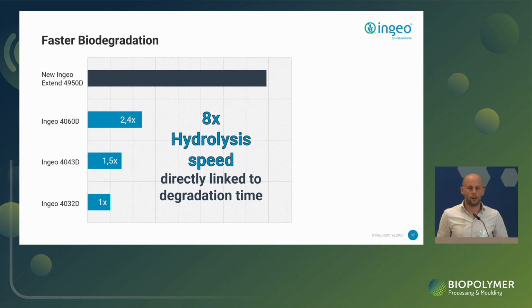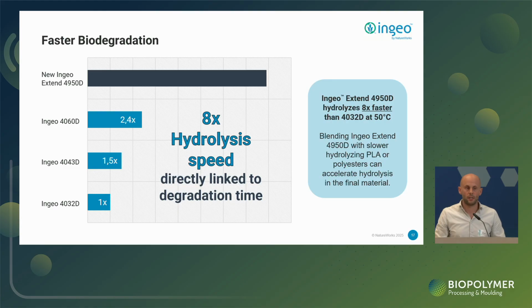Then talking about the biodegradation, what we found is that this new grade, Ingeo Extend 4950D, shows 8 times higher hydrolysis speed compared to a standard PLA grade. And the hydrolysis speed is directly linked also to the speed of biodegradation. That has been tested at 50 degrees C, so it means it's not under home composting conditions. This is really important to mention. But it should certainly help to overcome the challenges that some may have with PLA and the slower degradation. Obviously, if you are, for example, at the borderline with certain structures and need some faster degradation, that could really help to speed up the process.